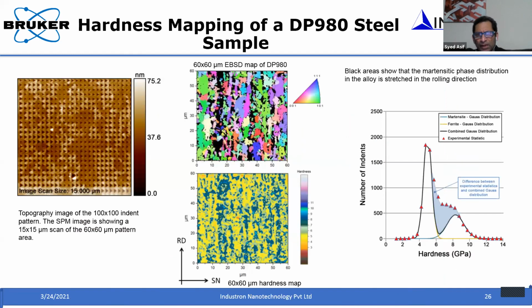Okay. Another example, this is done on a DP980. It's a steel, a rolled steel. And I mentioned in the previous slide that you can combine this with an EBSD map. For example, in this case, about 100 by 100, about 10,000 indents were done within 2 or 3 minutes. And this is a 15 micron by 15 micron scan. The EBSD image of the same region shows all this color differentiation, which is basically the crystallographic orientation. The black color that you see corresponds to the martensite. And if you now compare the hardness map below it, you can see how well it matches. You can see that the dark regions correspond to this dark blue region, which has the highest hardness. So you can directly correlate the crystallography or the phases that you see in some of the techniques to the hardness map. Okay, that's one advantage.